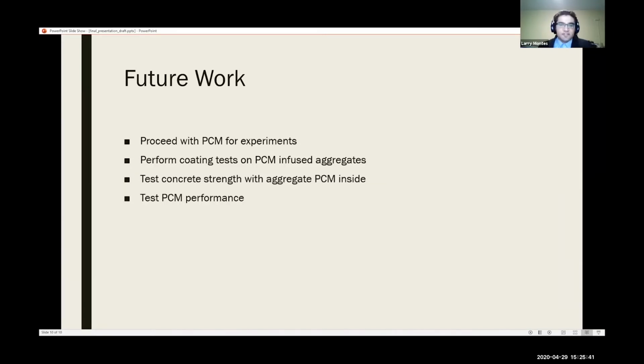So unfortunately, due to COVID, lab access was cut off when we were ready to begin experimentation with the phase change materials. And while we should expect similar results, we still need to test the coating of the aggregates with PCM inside. We also still need to test the compressive strength of concrete with the PCM aggregate inside to ensure that the mixture is capable of taking the strain caused by forces on the concrete in a typical setting.